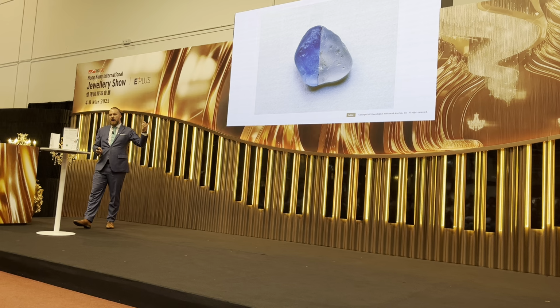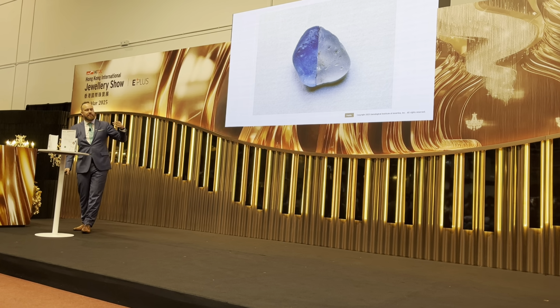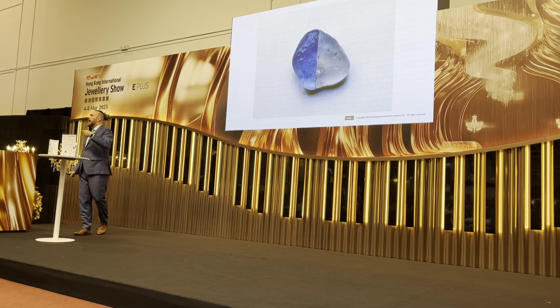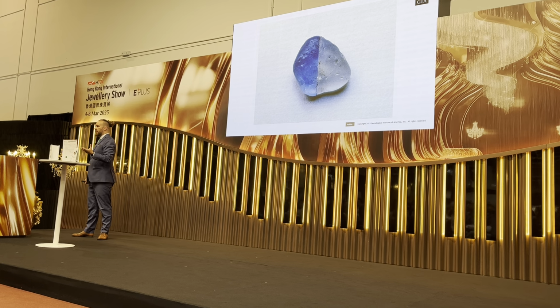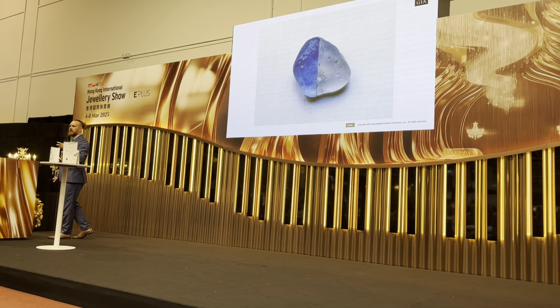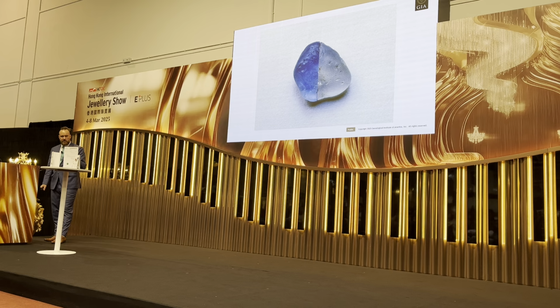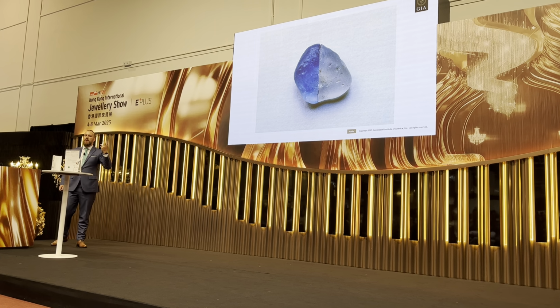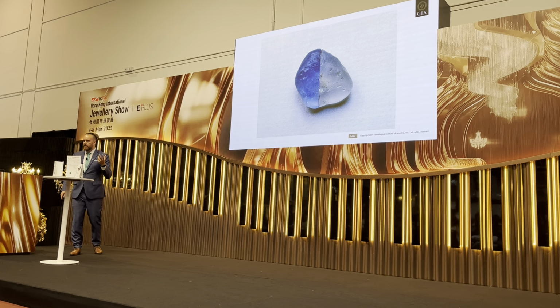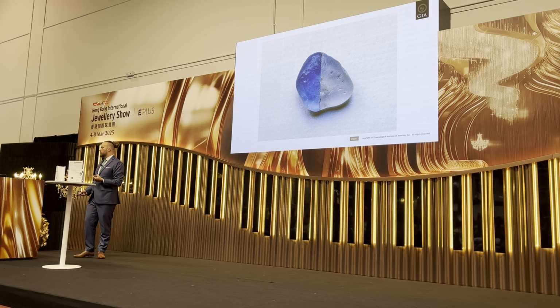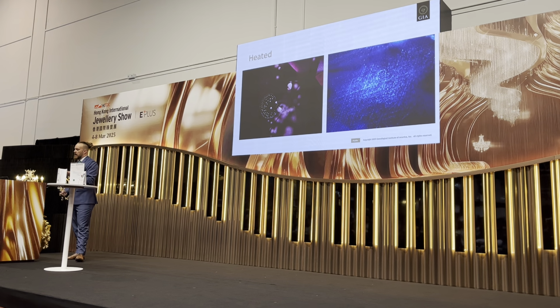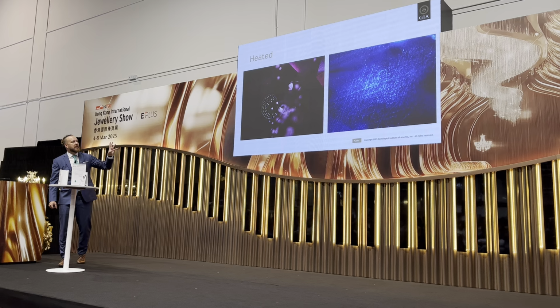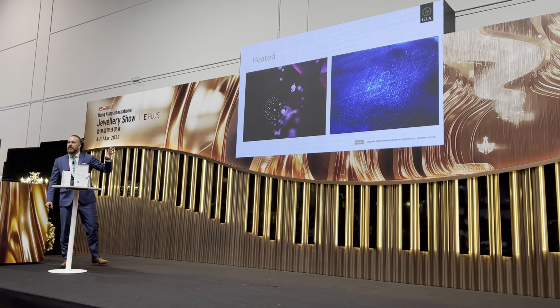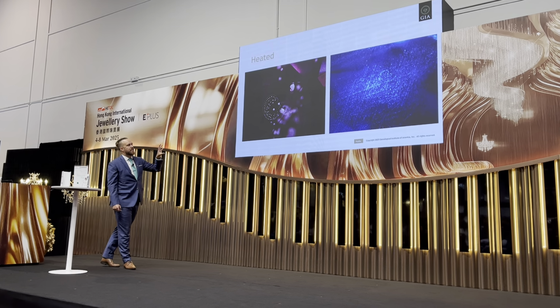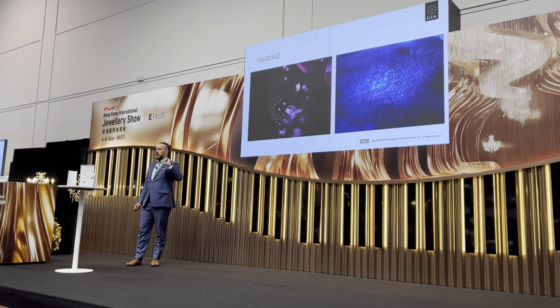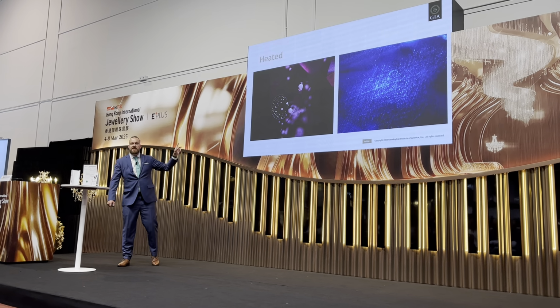Because this is the other half of the stone, where we can see that the color has drastically improved and the cloudiness is completely gone. So we were able to turn that milky, cloudy, whitish stone into a very beautiful, transparent blue pebble. So that is the 2 main reasons why we do heat treatment on rubies and sapphire. Now, detecting that often relies on the inclusions again, where we can see that the inclusions are completely different from what we saw in those untreated stones. Because these are very similar inclusions.